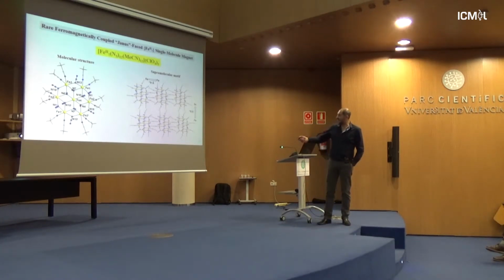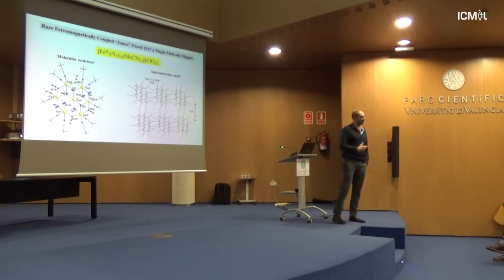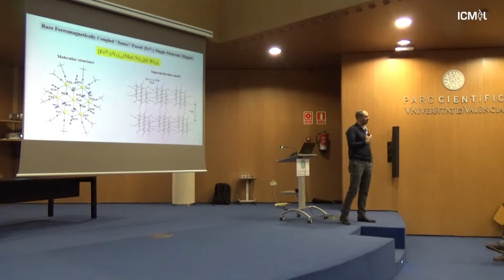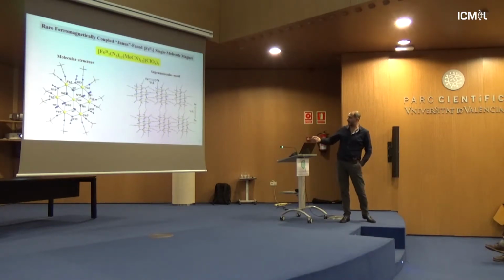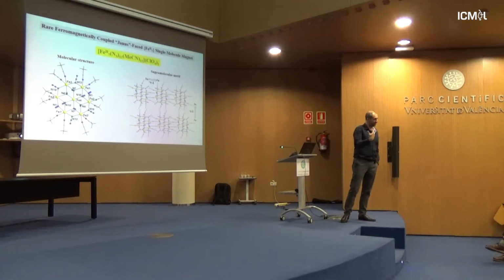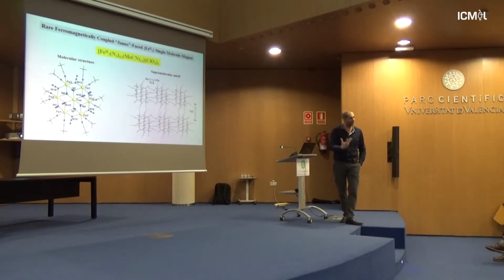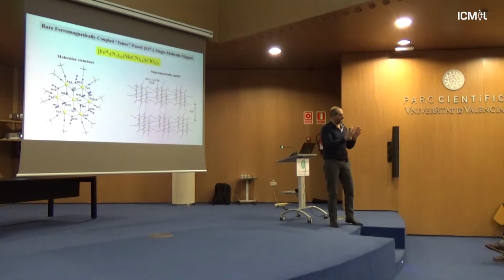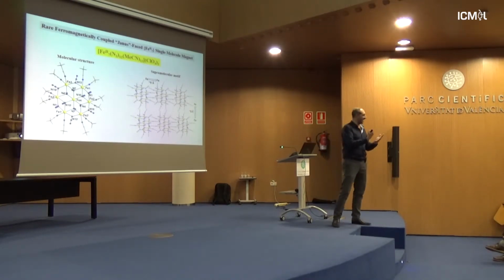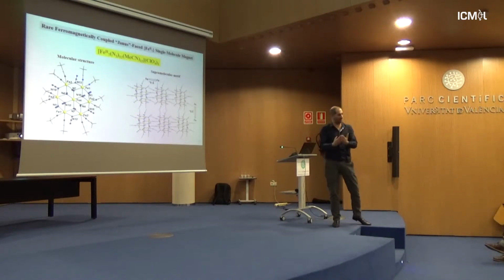If you look down this axis and down that axis, you see that the iron-iron separations are quite large, around 9 and 8 angstrom respectively. The question is why? Because the clusters are separated by those terminal solvate molecules, the acetonitrile molecules. This is what we call the wet sample: the sample which is not dried, where the metal ions retain their solvate molecules, and you can study it as is, the pristine form of the compound.